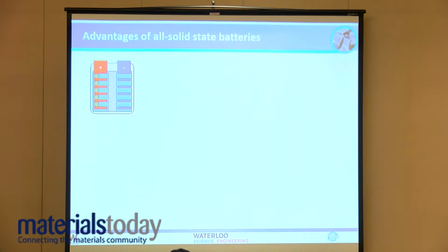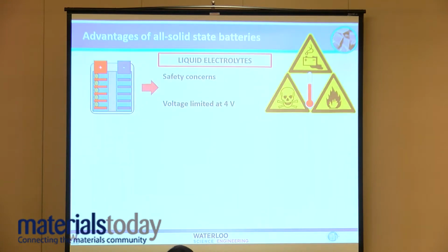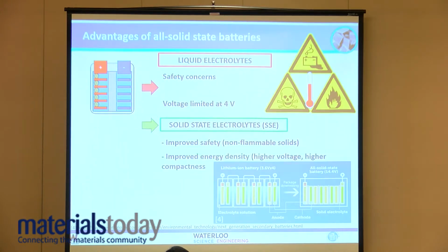So the advantages, if we take our lithium-ion battery, are that we don't have the safety concerns of liquid electrolytes. We don't necessarily have a voltage limited at 4 volts, because in principle, solid-state batteries can go up to 6 volts, as long as the electrolyte is stable. And that requires, however, a solid-state electrolyte, and it requires one that's chemically stable. So these have improved safety because they're inorganic materials, and especially they are compact.